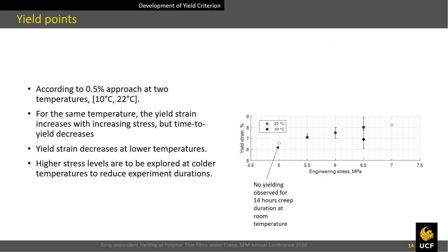Yield points are explored for different temperature and creep stress levels by varying creep durations as explained in the previous slide. The figure shows the current best estimates for the yield strain at 2 temperatures and various stress levels. In this figure, the yield strain is defined as the strain at the end of the test that corresponds to 0.5% residual strain.